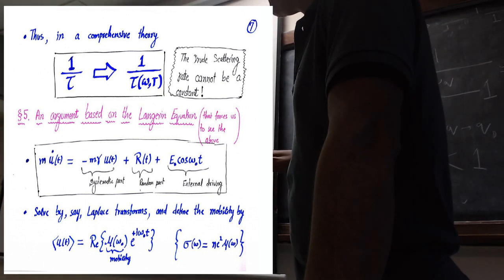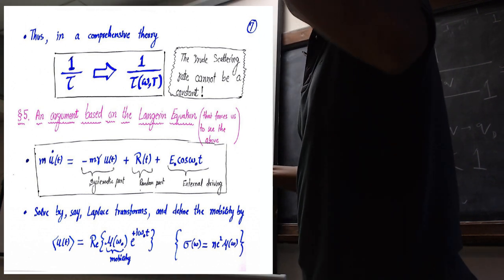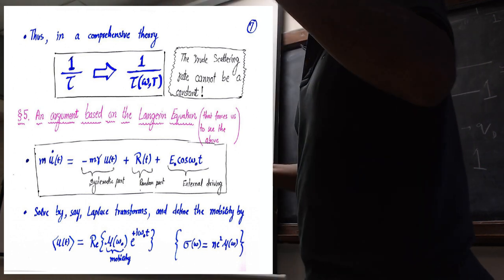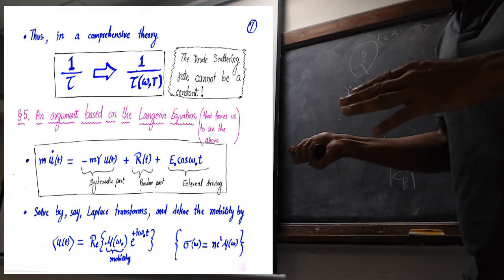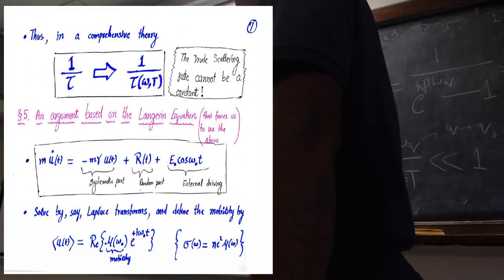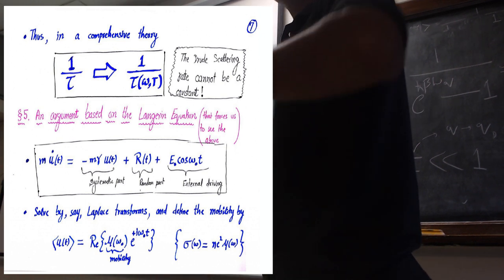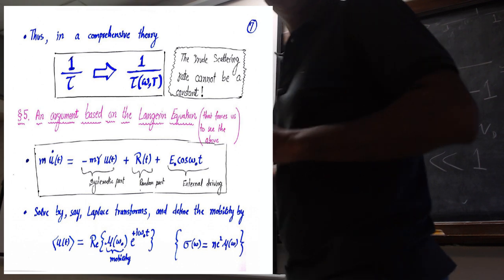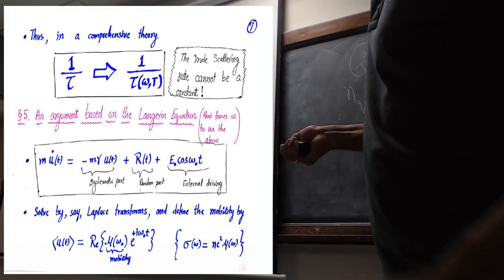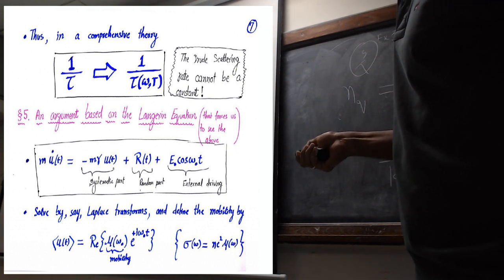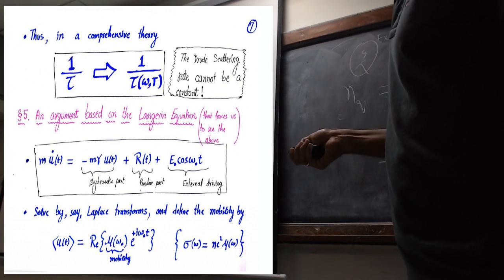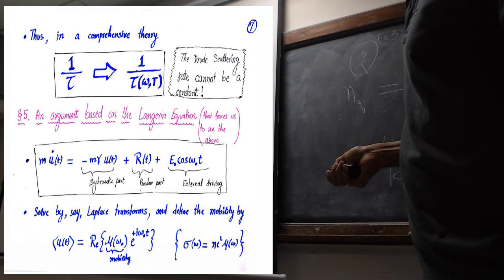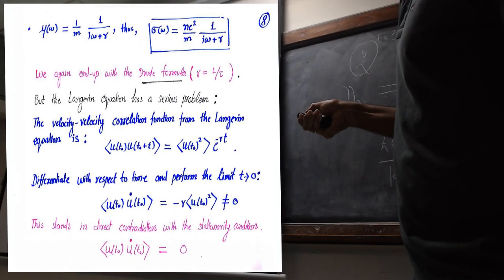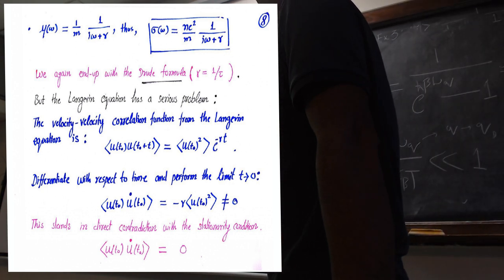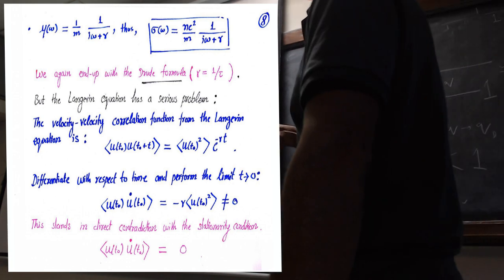So this is a drag, and this drag is very much like a stochastic drag actually. A falling water droplet in the atmosphere feels a drag which is proportional to velocity. This is the same drag, Stokes' principle. But at the same time, this drag must come in addition with this random force, R(t). R(t) is a vector which has a random direction, and R(t) and R(t') are not correlated. But then since the electron is a charged particle, you can have an electric field acting on it. Then you can solve this Langevin equation by doing some Laplace transforms, and you get the conductivity in terms of the mobility. And then the same Drude formula can be obtained from the Langevin equation. That is another way to look at the Drude formula. You can use the Langevin equation to derive it.